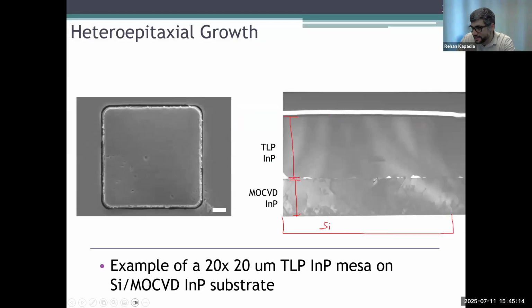Now, the key thing to keep in mind is that when you see any kind of line or zigzag, all of these sharp lines, they are defects. And so what you can see is that there's a huge amount of defects in this underlying material, which is exactly what we would expect. What we did not expect is that if you look at the interface between these two, the defects don't seem to propagate through, and that's quite unexpected. It's not something that we would have anticipated when we initially did this, for multiple reasons, but let's just focus on this.